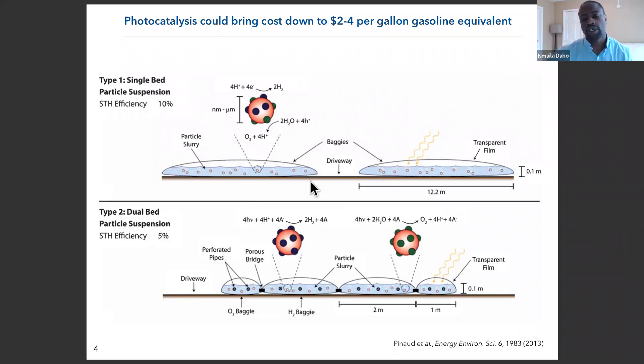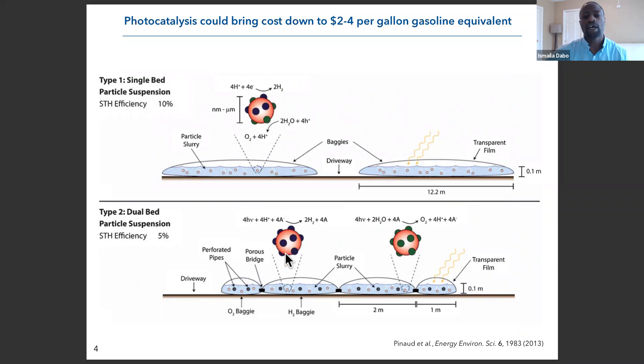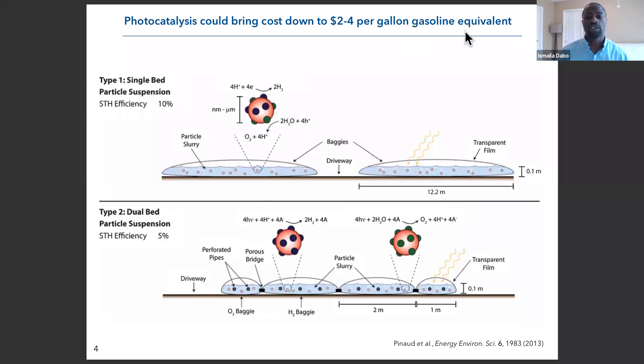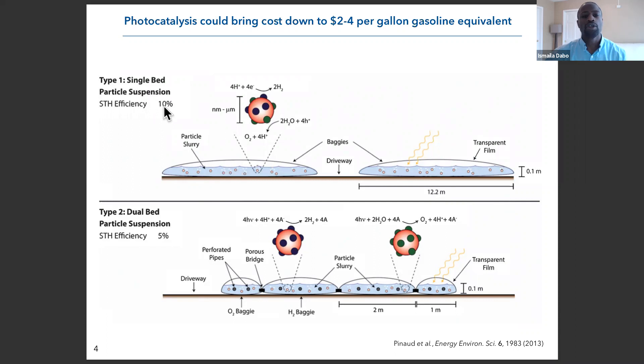There has been a lot of analysis of this type of technology. In particular, a nice paper published in Energy & Environmental Science in 2013 analyzed the techno-economic feasibility and concluded that if you achieve a solar-to-hydrogen (STH) efficiency of 10% — the current threshold — you could bring down the cost of producing hydrogen to $2–$4 per gallon of gasoline equivalent, making it competitive with regular gasoline. The caveat is that we don't currently have materials that can achieve this efficiency, and it is a challenge for both theoretical and experimental communities to develop stable and scalable materials.